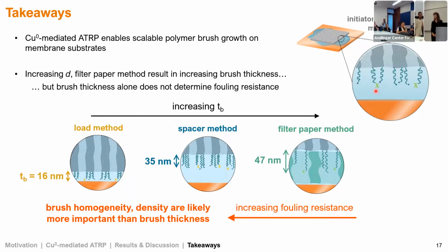If you were to use these anti-fouling films in a real application, would you expect any changes in the selectivity or permeation of the films, through the membrane? Definitely. That's another optimization point: as we're adding material on top of our membrane, potentially blocking the pores, we do expect that to affect permeability.